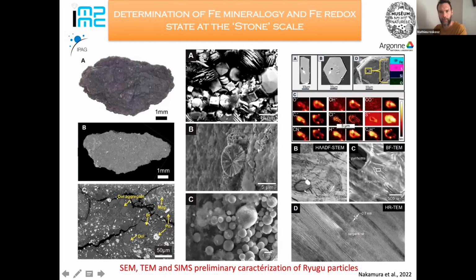We also have a lot of pyrrhotites, and in some of the pyrrhotites, I think it's Mike Zolensky from NASA, was able to find inclusions, and analyzing the inclusions, he was able to show that there was CO2 and H2O trapped in this pyrrhotite, which gives us an idea of the temperature at the place in the solar system where these materials got formed. It was pretty cold because it had to be beyond the CO2 ice line. So it was more or less where Neptune is now, so pretty far from the sun.